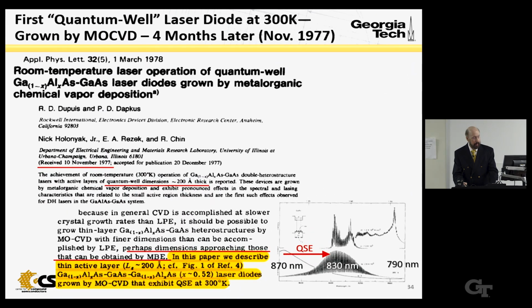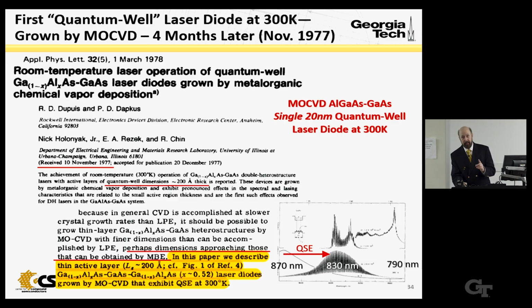And this is the result. As I mentioned, this is a single quantum well. I didn't need 5 or 20 or 50 pairs for enough gain. I had enough gain on one quantum well to get a laser. And not only that, it was 20 nanometers. And as you can see in the spectra, the quantum size effect shift was dramatic from 870 nanometers, where the band gap of gallium arsenide is at room temperature, to 790 nanometers in the upper quantum state. So we saw not only the first quantum transition, heavy hole to electron, we had light holes, we had the second quantum state, the third quantum state.